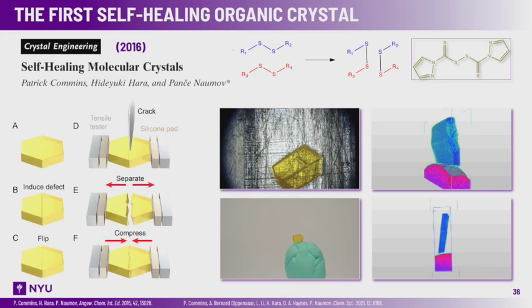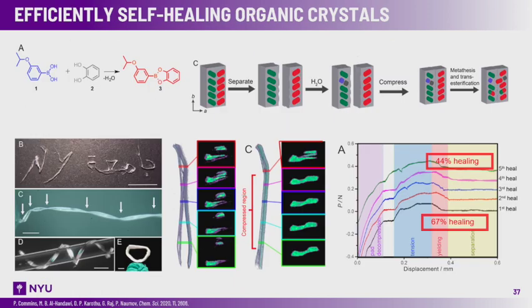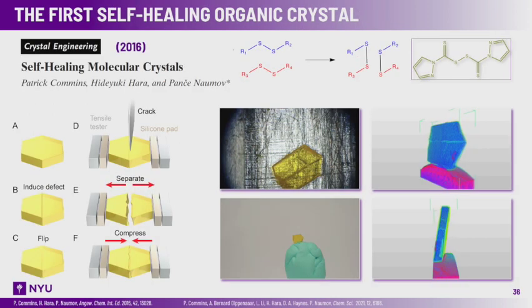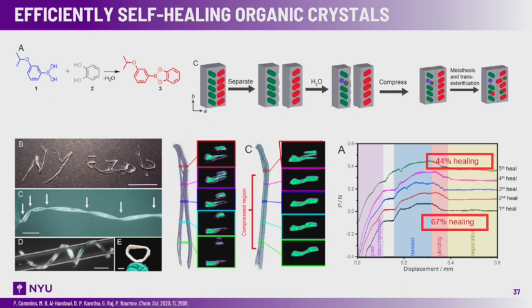But if you want a more quantitative way of looking at it, you can use computed tomography to look throughout the crystal and see what has happened inside, and we find that it has healed in its interior. Unfortunately, in this case, the self-healing was very small, about 7%, but now recently we have increased this with a completely different chemistry, which is boronate chemistry, to 67%, so one order of magnitude in the healing in the first cycle, which drops back down to 44% in the fifth cycle. So we have also now tried other compounds, especially perovskites, and it's working very well in the single crystalline state.